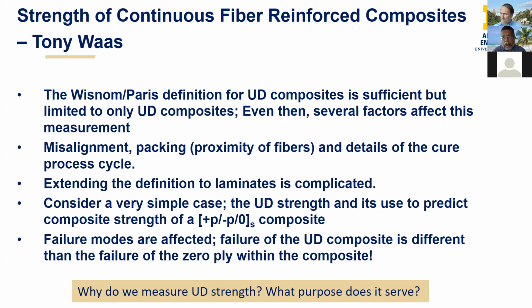It's stochastic because the fiber strength is stochastic, and the misalignments and voids and other defects can also be stochastic. The residual stress state is not uniform at all. That's stochastic as well because it depends on the packing. All right. So if you put all that into the question here and consider this challenging problem, you find 2 important things happen.